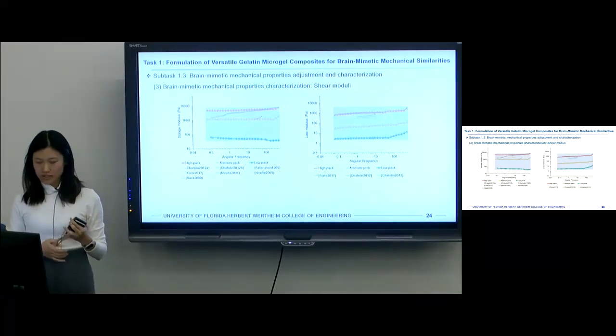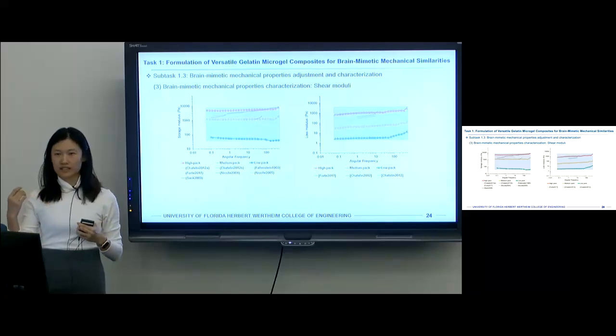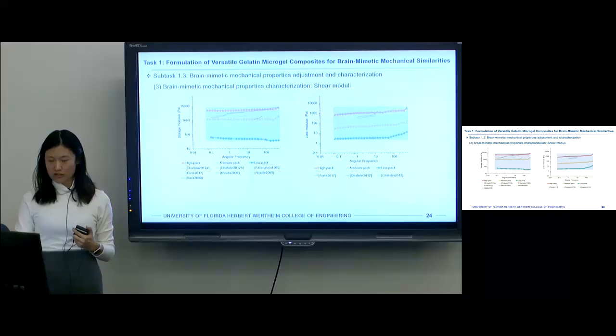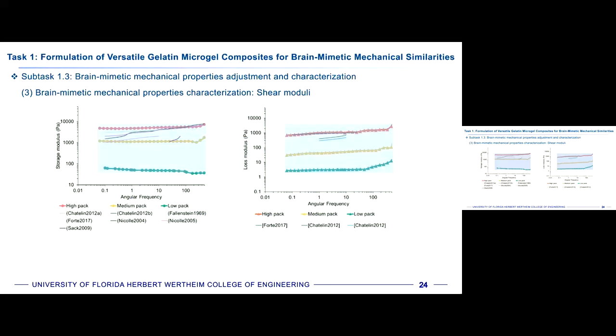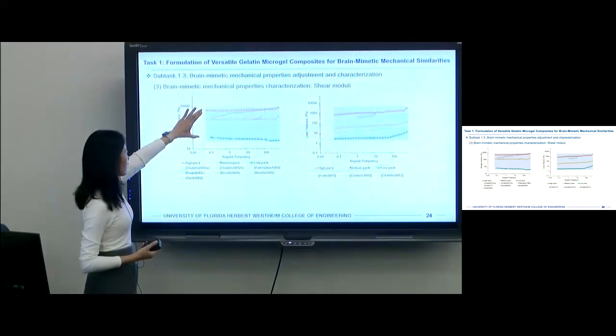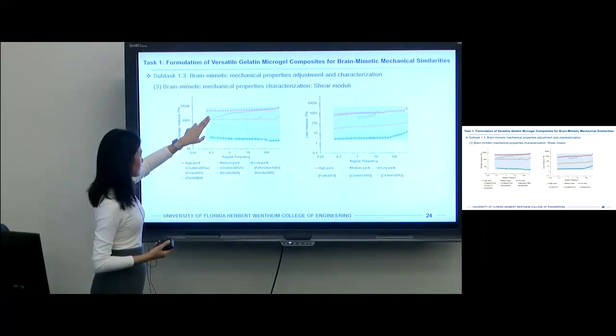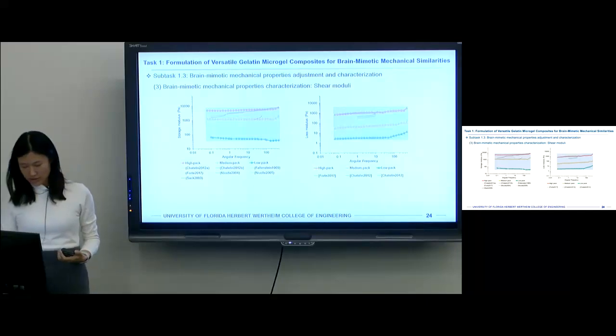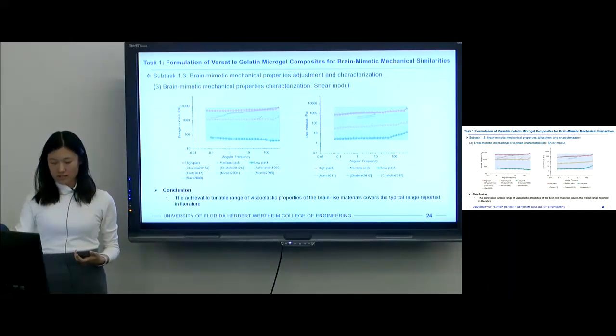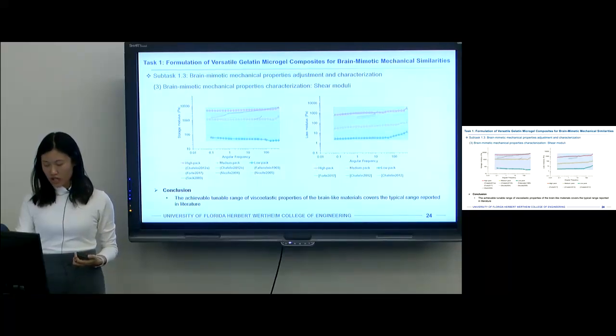And in addition to the Young's modulus, we also did some rheology property testing. The boundary lines are the samples we measured, and it can cover the reported data shown in previous literatures. So the conclusion is the achievable tunable range of the viscoelastic property of the brain-like material covers the typical range reported in previous literatures.